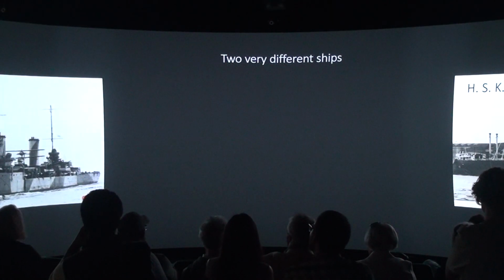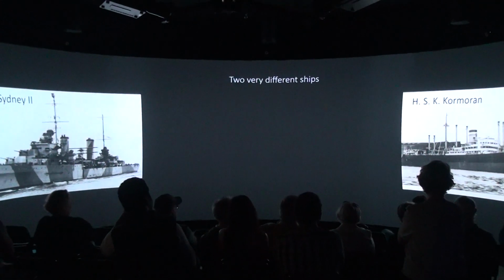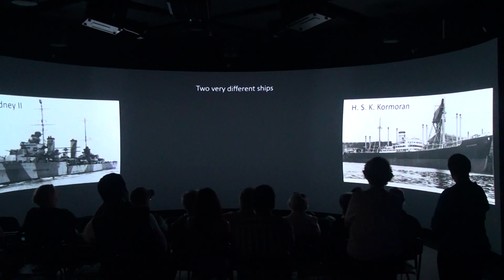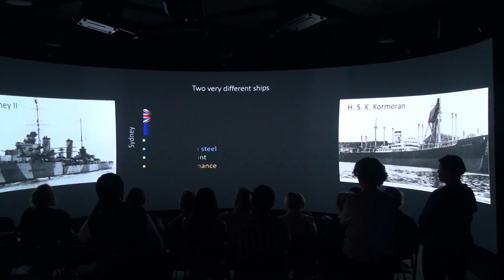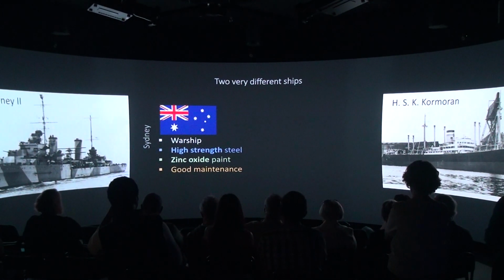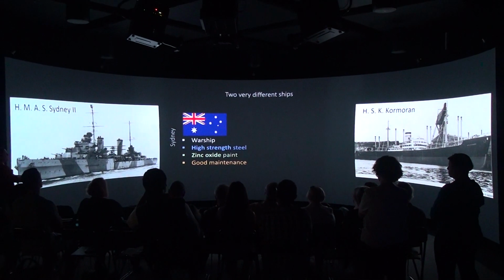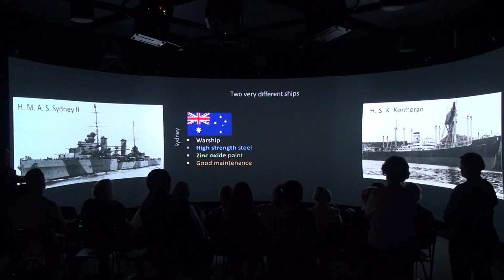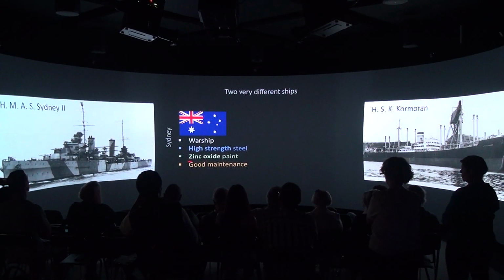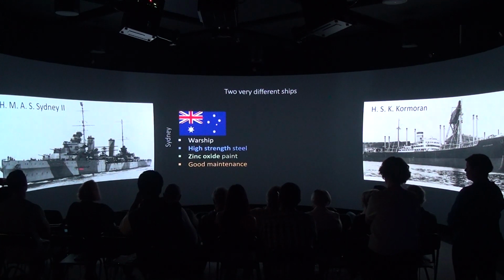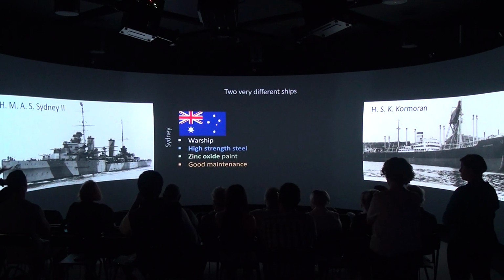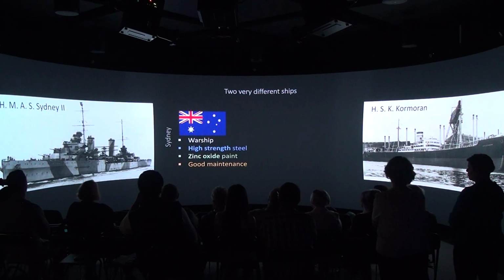So why is there such a significant difference between the Kormoran and the Sydney? They are two very different ships. Here you can see the Kormoran with the previous name when it was a merchant ship, as Laura was saying, and here you can see the Sydney, a full-on warship. So that's the difference. The Sydney was conceived as a warship, therefore it had high-strength steel. It has a very well-maintained zinc oxide paint, and regular changes of the camouflage, regularly pulling out the whole ship and putting it in a dry dock and cleaning the whole hull.